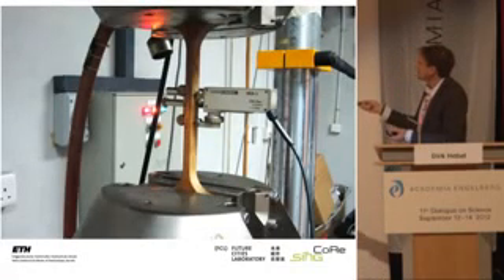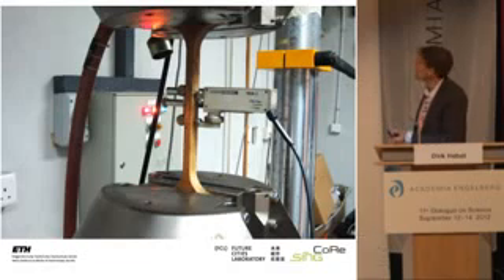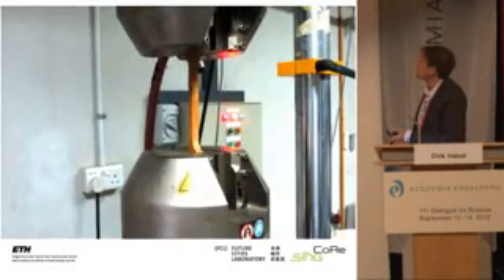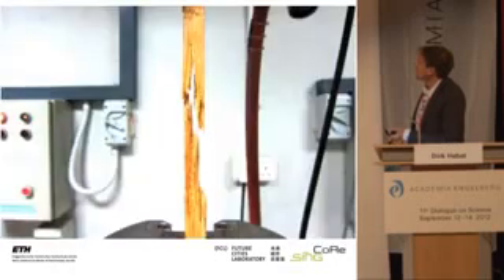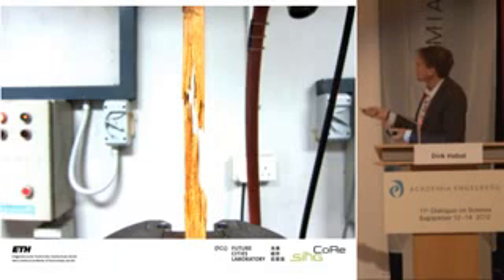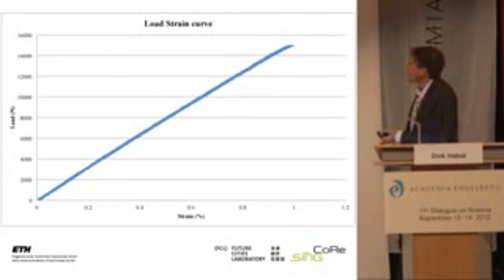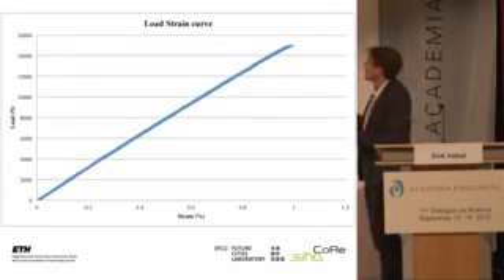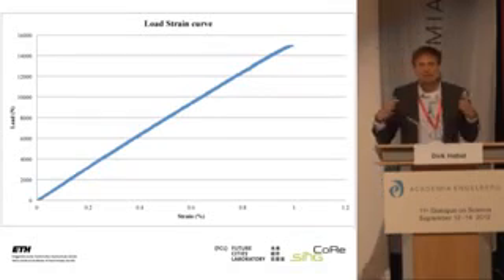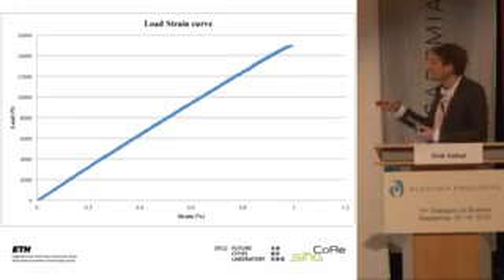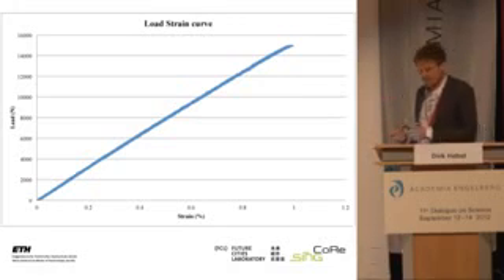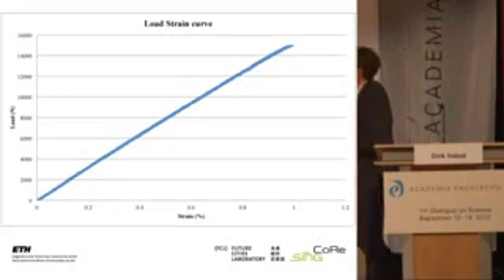We do the same as with bending, so we're not only testing the tensile strength in the fiber direction, but also the bending capacity of the bamboo composite. And basically, you see here the failure then, so you pull on both ends until all of a sudden you get these fractal splits of the material. And right now we have graphs showing that our initial assumptions are correct, that with the process we can keep the strength of the material as we like.